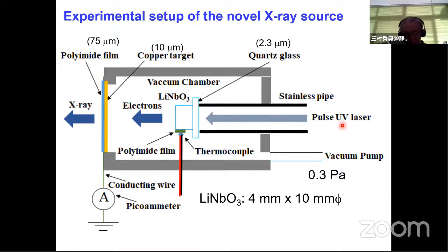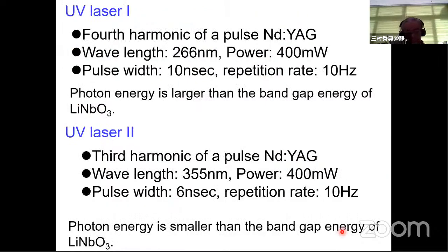We use a pulsed UV laser to excite the lithium niobate crystal. We use two pulsed UV lasers. One is the fourth harmonic of the pulsed Nd:YAG laser. The wavelength was 266 nanometers. The power was 400 milliwatts, and the pulse width was 10 nanoseconds. The repetition rate was 10 Hz. The photon energy at the wavelength of 266 is larger than the bandgap energy of the lithium niobate.